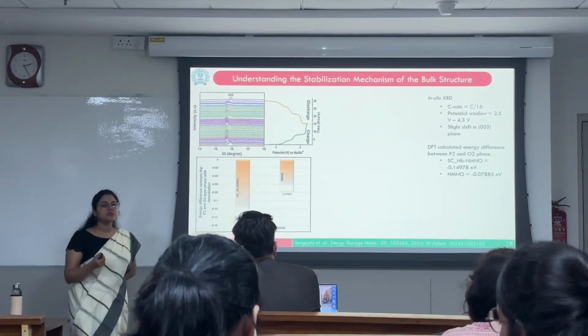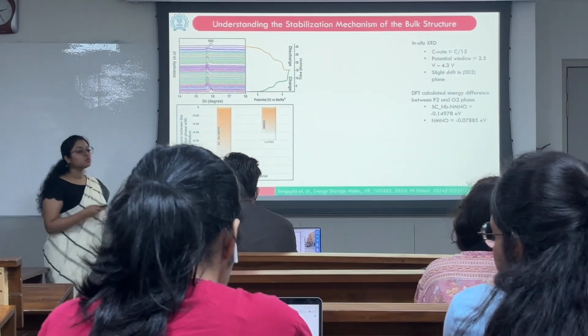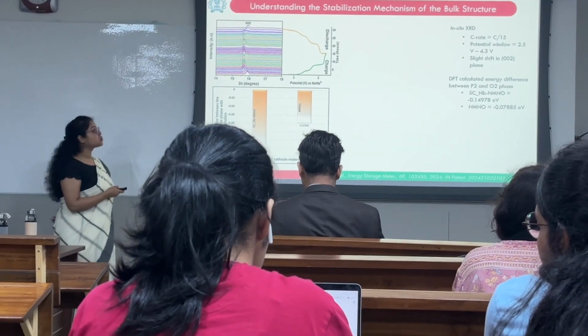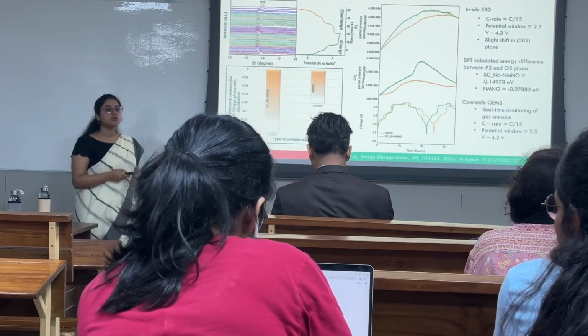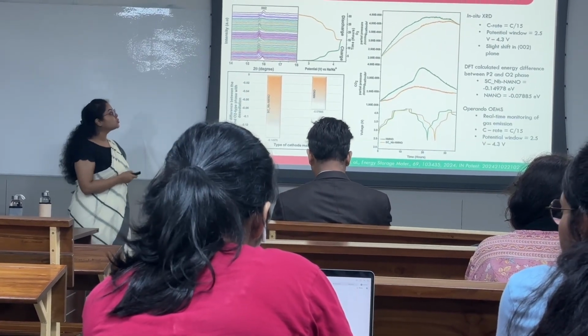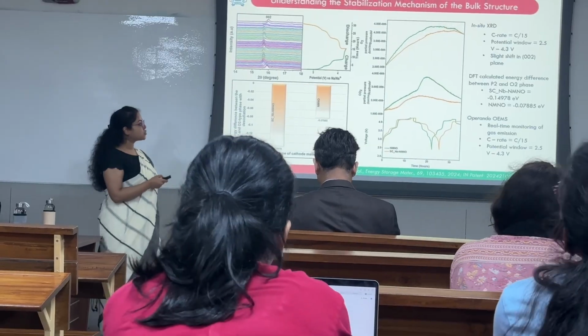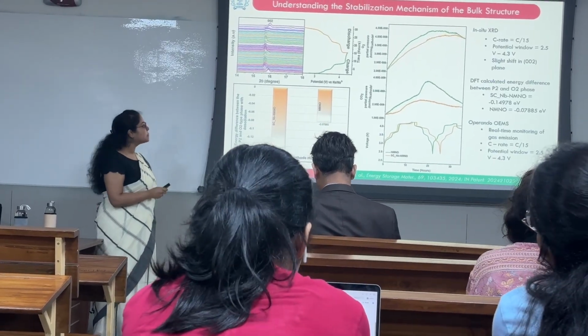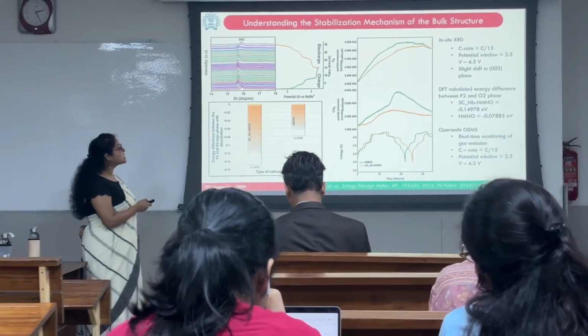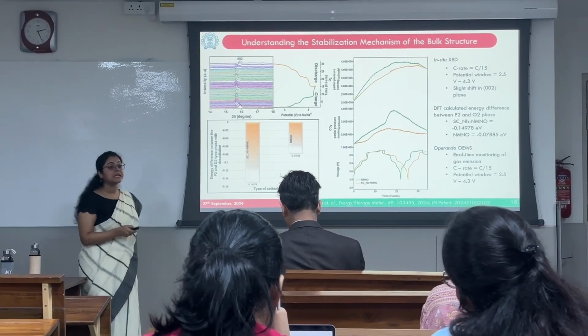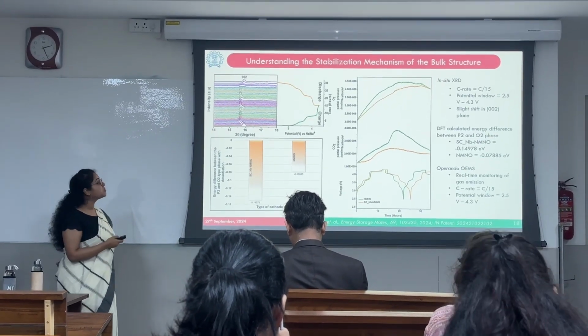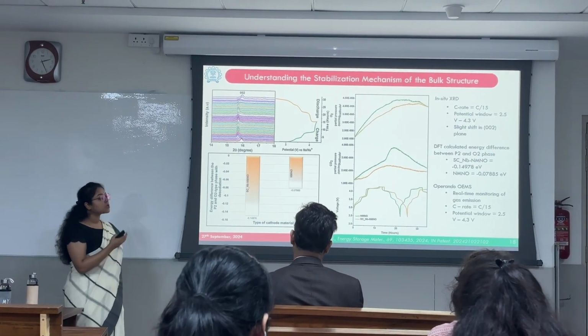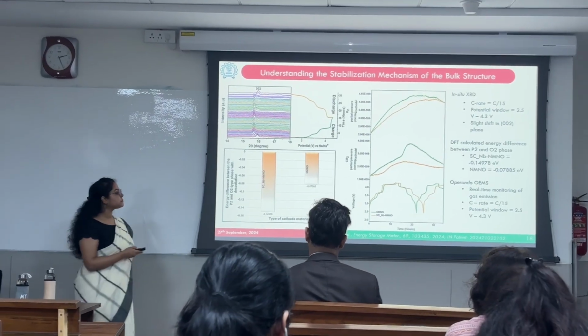Since in situ X-ray diffraction is also related to the gas evolution in the structure, we conducted a real-time monitoring of the gas emission through the online electrochemical mass spectroscopy at a slower C rate of C by 15 and observed that the CO2 evolution was significantly lesser in comparison to that of the pristine one. However, even the oxygen gas was suppressed.